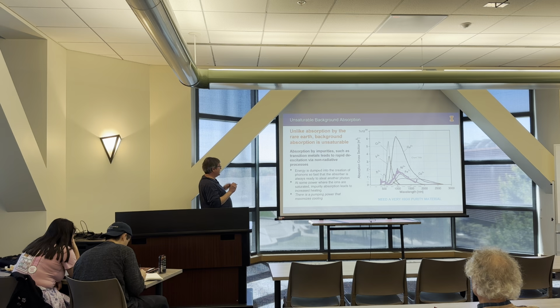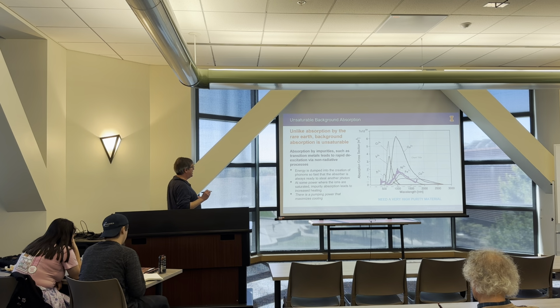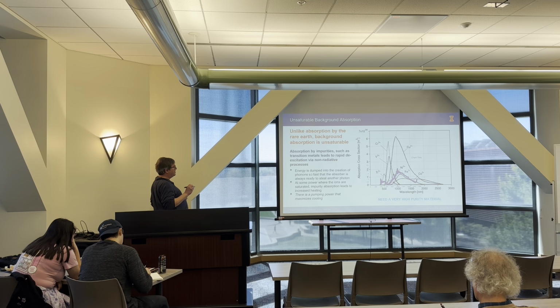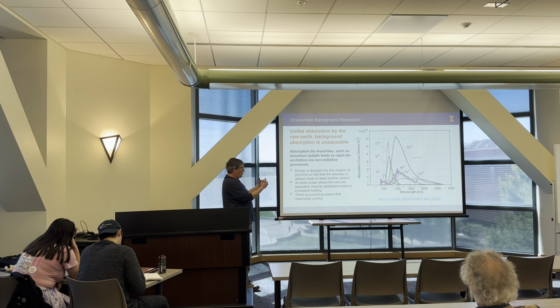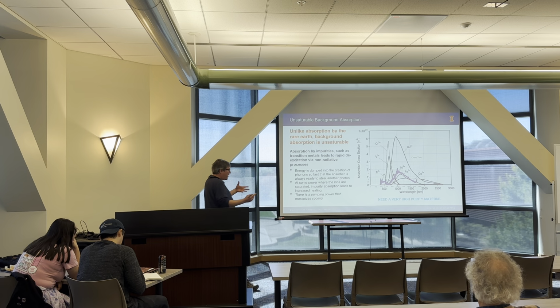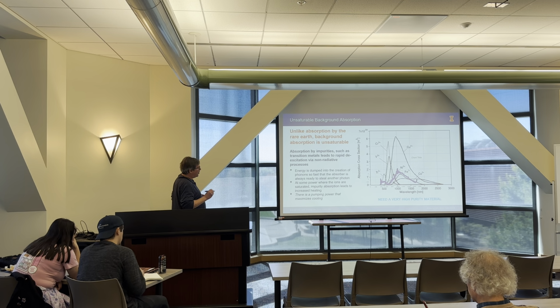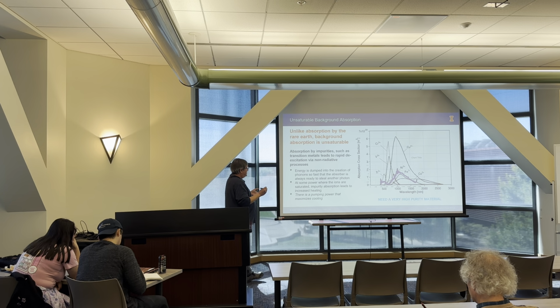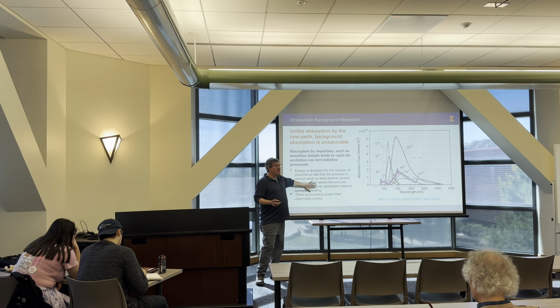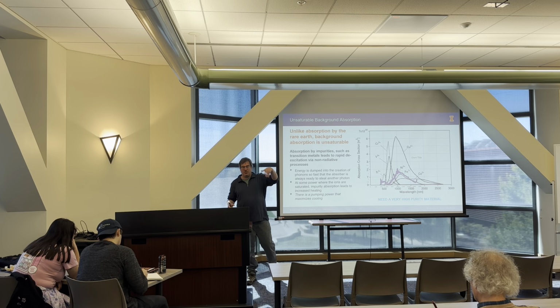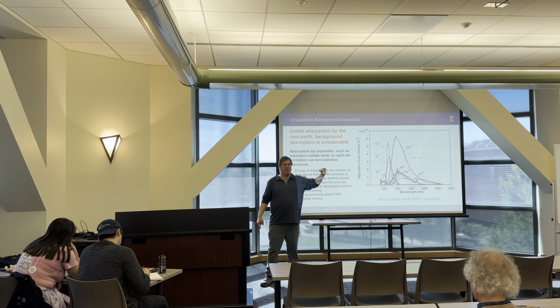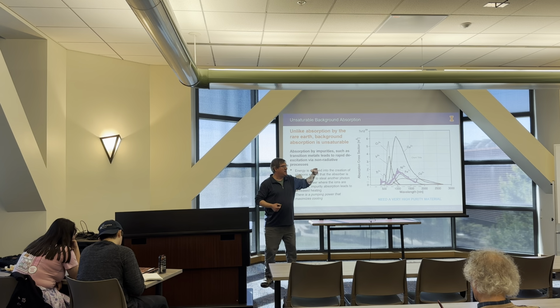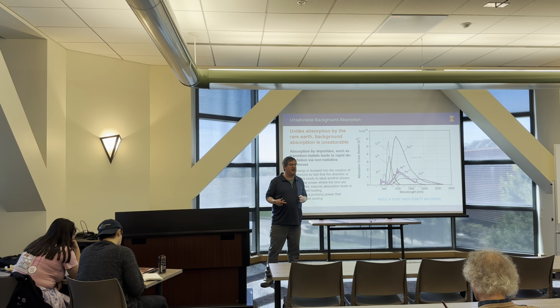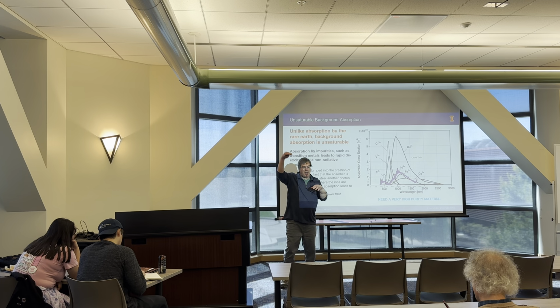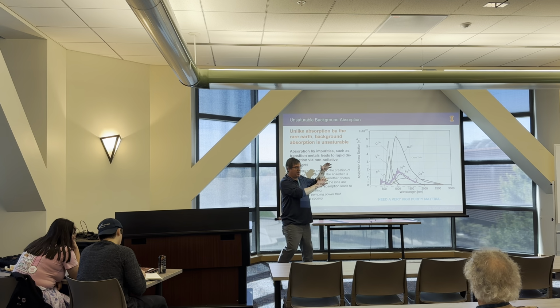Like I said, rapid de-excitation is a non-radiative process. Energy is dumped into the creation of phonons really fast. So those impurities are always there, always ready to absorb, and of course this is a form of heating. So there's a competition: first you're doing the anti-Stokes fluorescence, but then you run out of ytterbium emitters. You're cranking up the power, the ytterbium can't absorb anymore, and you can't get any more cooling, but the impurities keep absorbing those photons. And so what was cooling initially turns into heating eventually, with enough power.